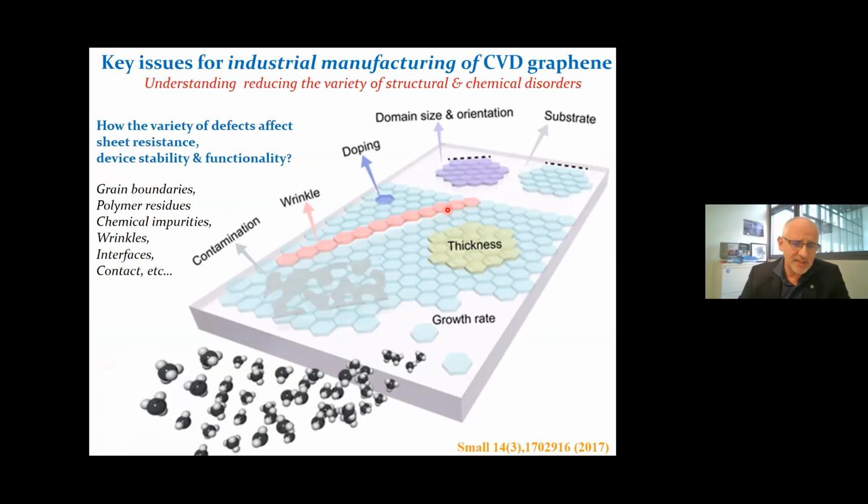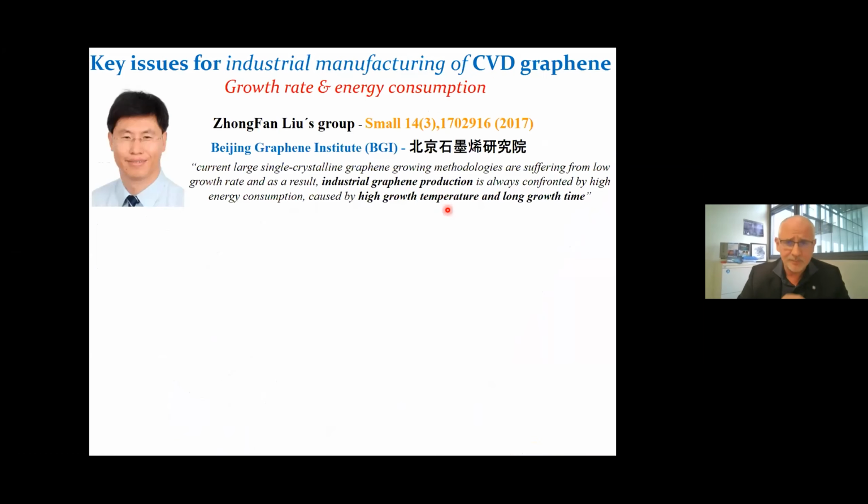But there are also additional sources of contamination when you detach your graphene or 2D material from the metallic substrate and transfer it to an oxide substrate, for instance. So you have to develop these processes to be as less invasive as possible, and you have to deal with that. But grain boundary is really one of the central questions. Do you need a single grain for a target application, or can you deal with polycrystalline graphene with a much smaller grain size? That's really an open question.